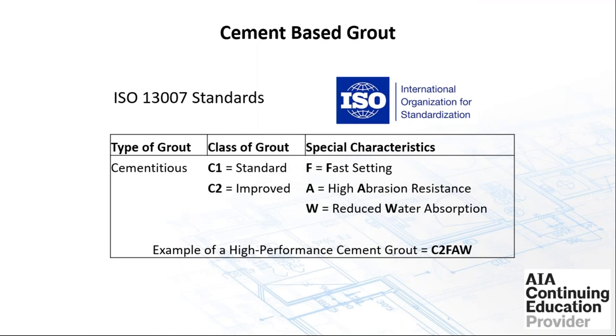Here's the ISO standard, a very good example of how it's broken down. If you specify a C2 improved FAW, fast setting, high abrasion resistant, reduced water absorption, you go to the job site, and a lot of manufacturers have their particular ISO standards on the bag. You happen to visit a job site and say, I specified the C2 FAW. However, on the bag, it says a C1 standard. There's something wrong here. So again, like I mentioned before, it's about having the product you specified on the job site. ISO standards really help getting to that point. Well, I can't say ensure, obviously. Things can change, but it really helps with the process, and hopefully getting the product you specified on the job. ISO standards, can't say enough about them.